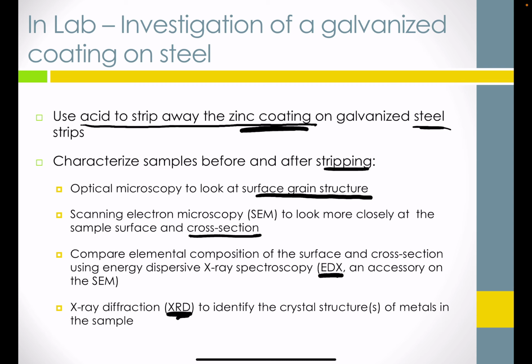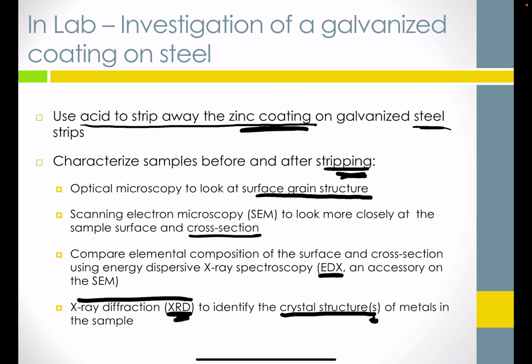X-ray diffraction, XRD, is a method that can interrogate the crystal structure or structures that are present. And so we may see that the crystal structure of zinc may be present at the outermost surface. Perhaps some of the other intermetallic phases below might present themselves in the XRD. And certainly after an effective stripping, we might see a new lattice pattern develop in that XRD data owing to the metallic iron or steel that is below, and that being the new surface and new material interrogated by the XRD technique. All right, and that should be how we're interrogating the galvanized steel coating.